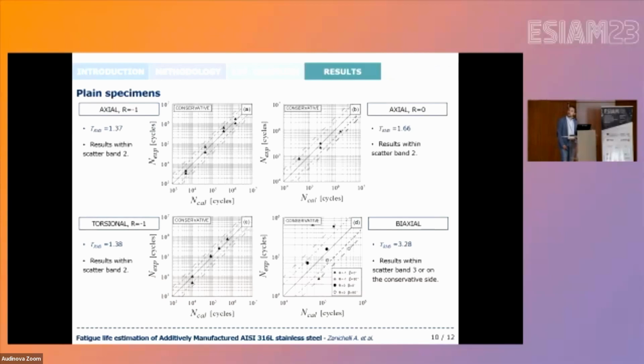So we obtained actually a TRMS value lower than 2 for both axial and torsional fatigue loading, whereas in the case of biaxial fatigue tests, we have a TRMS value slightly higher than 3, but let me say that in this case, statistical considerations are quite unreliable due to the very low number of specimens tested for each loading configuration.